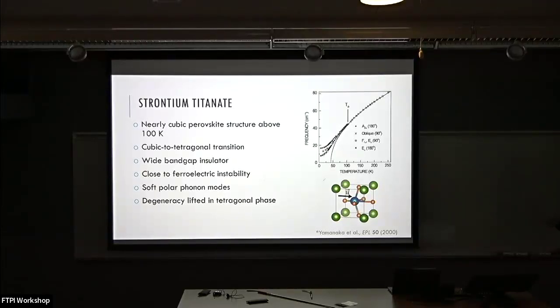Again, I'll basically do a very quick reminder of some things, but most of this you heard in Peter's talks. Now, one thing I would like to point out here is that, as Peter mentioned, there is a tetragonal transition in the system at 100 Kelvin, and this splits the soft polar mode. This splitting is usually ignored. For us, it's going to be quite important for technical reasons and for fundamental reasons. But just keep in mind that it is quite significant. So at the lowest temperatures, it's about a factor of 2. This lower mode actually falls below 1 meV, so it's really a super low energy.